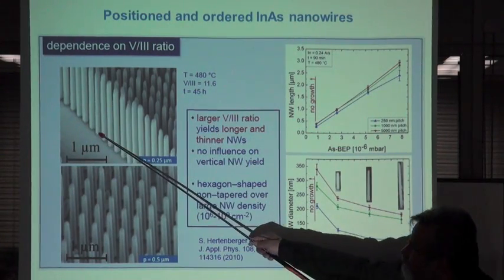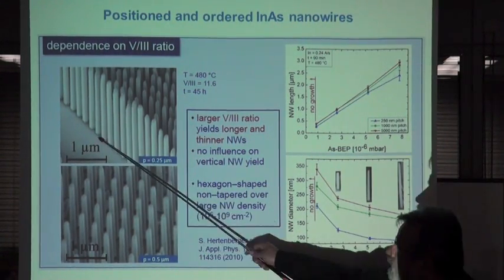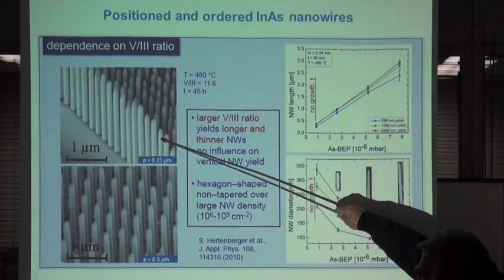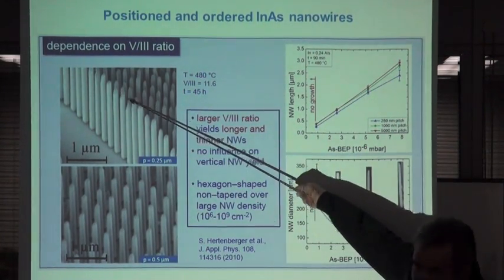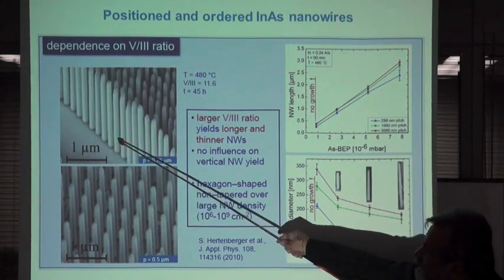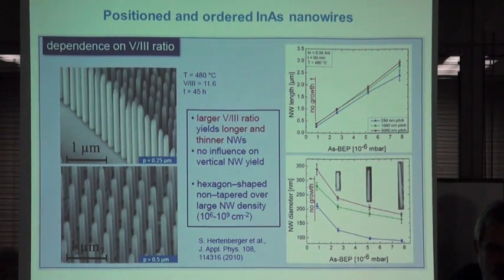This is the edge of one of these patterned fields, so there is nothing outside. However, the wires at the outside are slightly larger, and that's because they can collect more material from diffusion from the outside than inside, because this is limited by the pitch distance. If you change the pitch, make them further apart, then you can also get very homogeneous height in this system. So these are some examples, growth parameters. So we can grow thick or very thin. The thinnest nanowires we have grown at the moment are 20 nanometers in diameter.